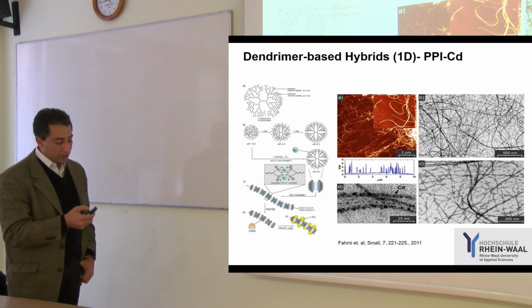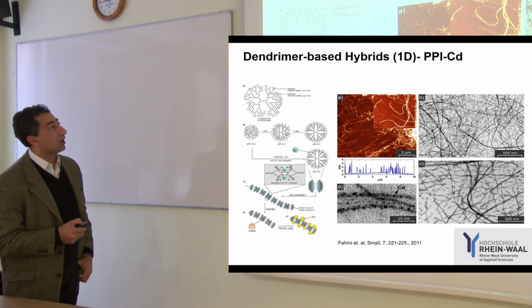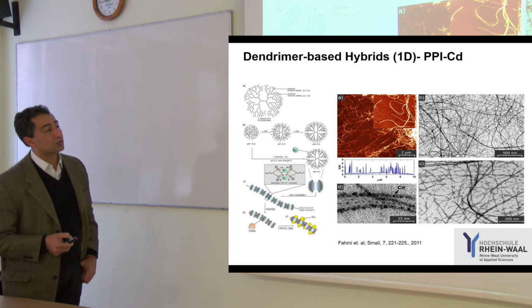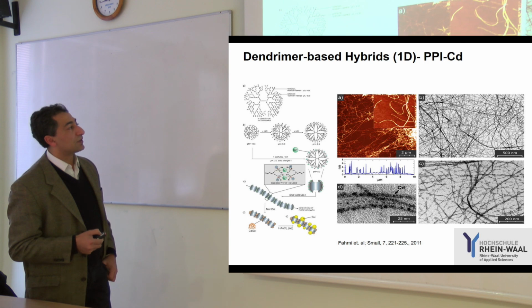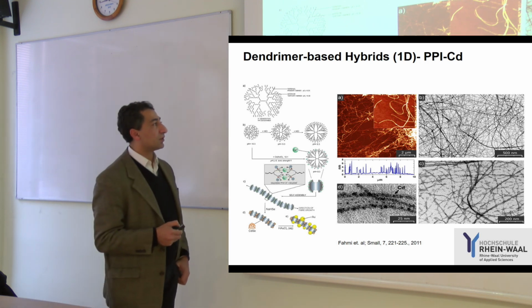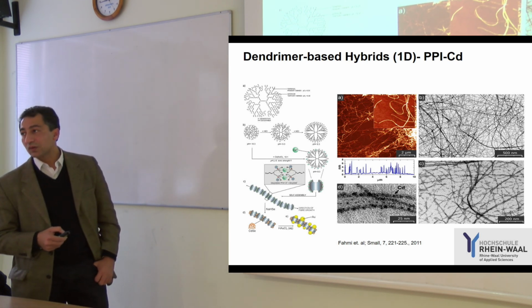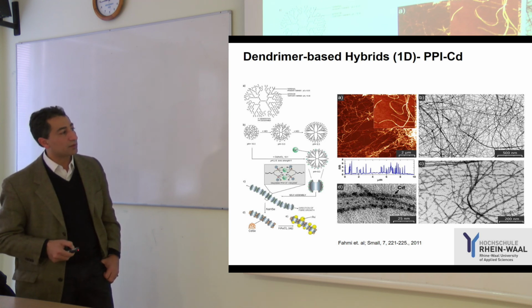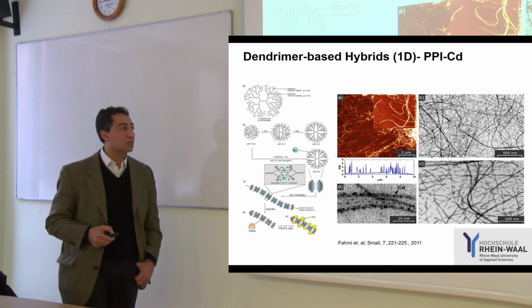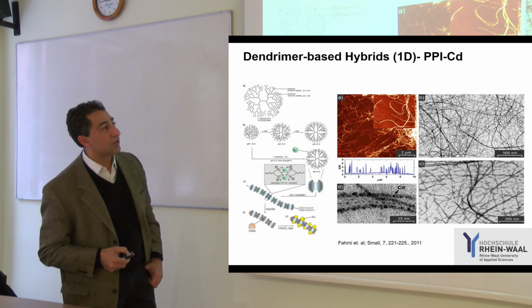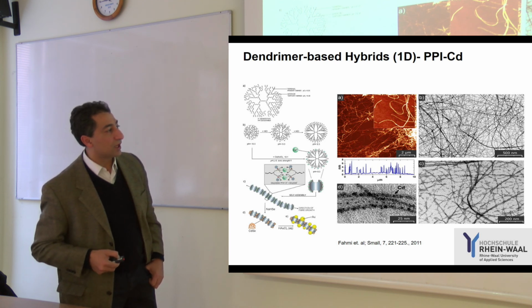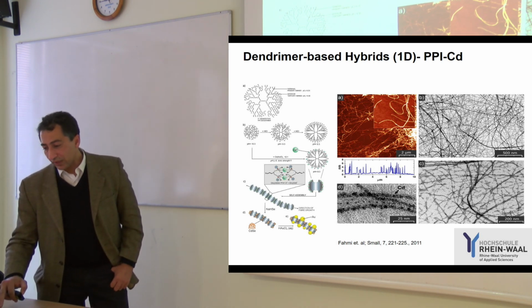As mentioned before, dendrimers have unique properties, with a large number of charges, and the good news is we can switch this charge and use it as a building block to have a large number of nanofibers with very high aspect ratio. As you see here, we have the dendrimers, we can put in different generations, and we looked at different inorganics. In this case, we use cadmium, and I will tell you later why we use this inorganic material. We can have this very nice wire using one metallic structure, in this case cadmium, aligned across the fiber structure. This transmission electron micrograph shows, even in high resolution, how the inorganic aligned inside the dendritic matrix. That was quite a nice start.